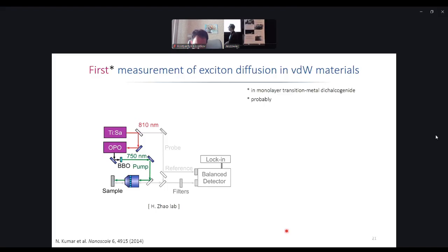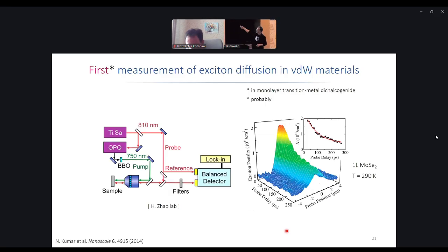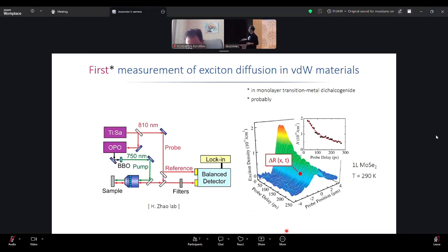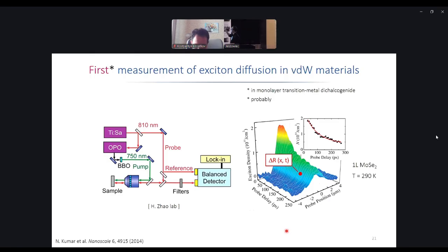So there is a pump which goes through a microscope onto the sample. The colors are obtained by photomixing. You have a probe that also impinges on the sample, and then in principle you can use this mirror, for example, or that mirror to control the spacing between the two, and then there is a delay line somewhere in between that will delay one pulse against each other, and then the detector, and this is the type of data you get. So here, on this type of data, each measurement point corresponds to a fixed position of the probe, fixed delay, so all the mechanics are set, and then the measurement is done and the signal strength is evaluated.